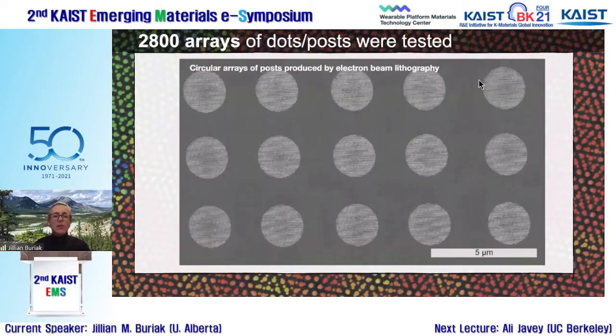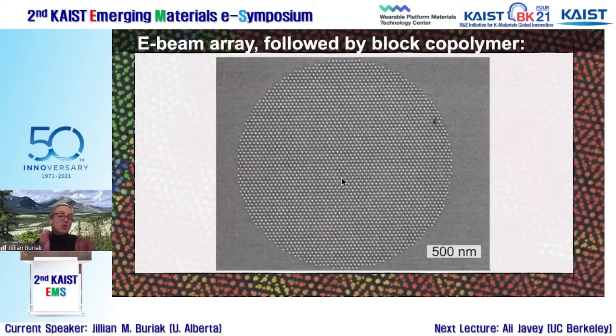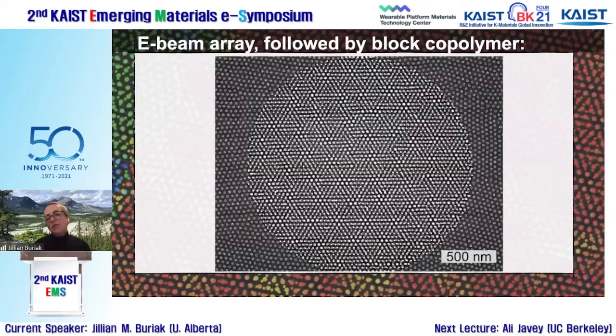So these are just some of the circular posts that he made by e-beam lithography, 5 micron scale bar, so you can't resolve the individual dots, but here's one. So again, we're not using the block copolymer to do the first one, we're using e-beam, so we can have precise control over the spacing. And when you put a block copolymer, polystyrene-PDMS, on there, again, you see Moiré superstructures all over the place. So with 2,800 combinations, we saw Moiré superstructures everywhere.